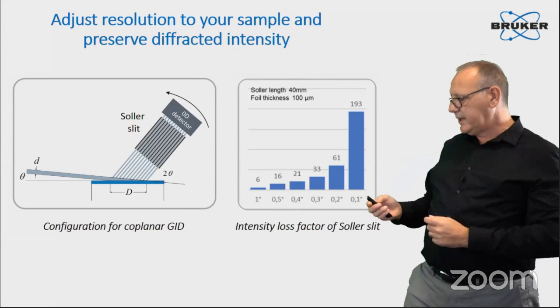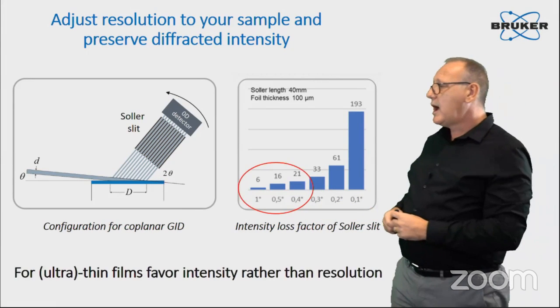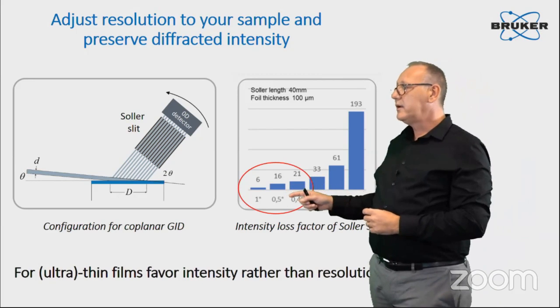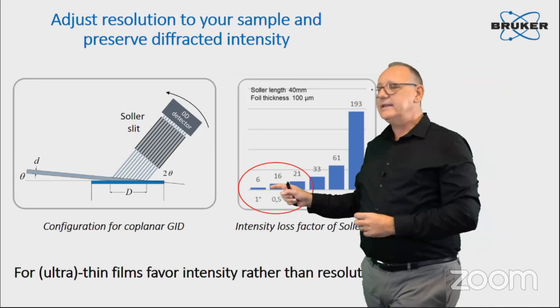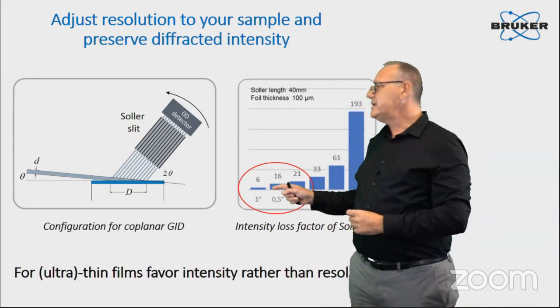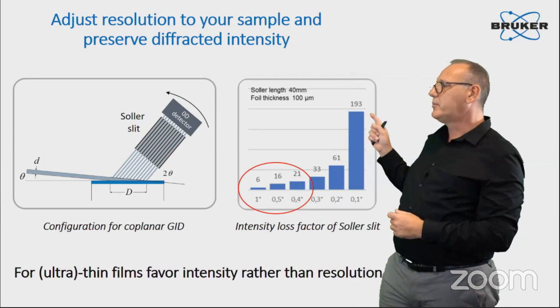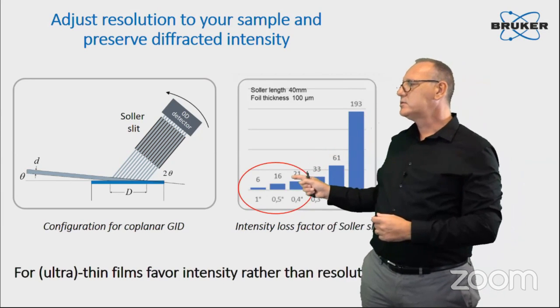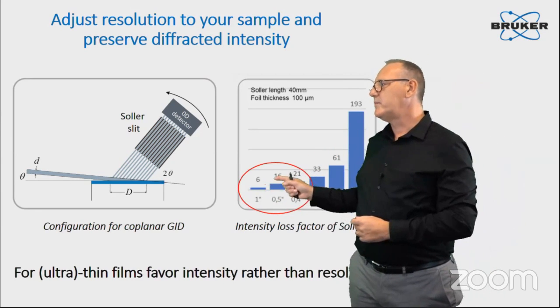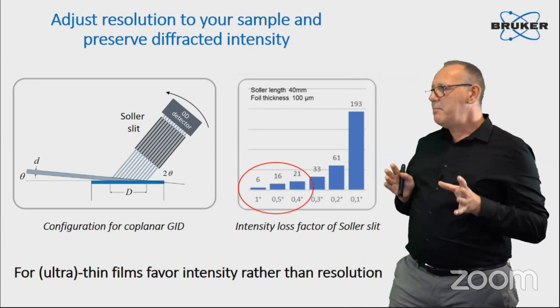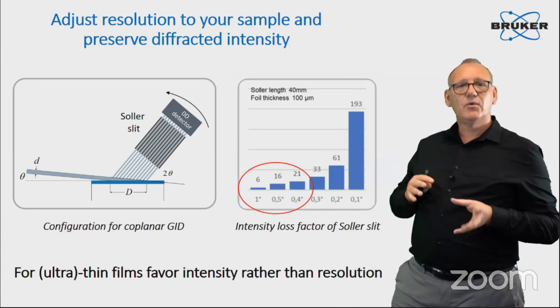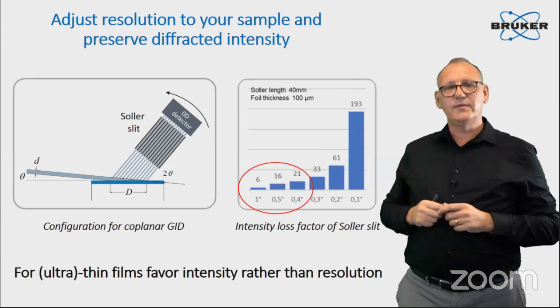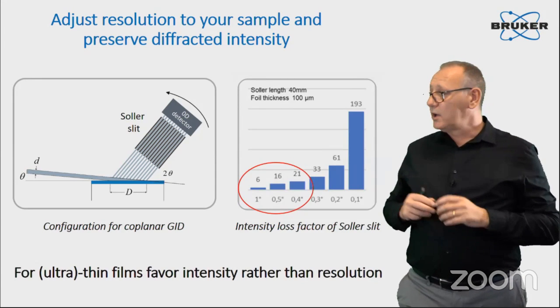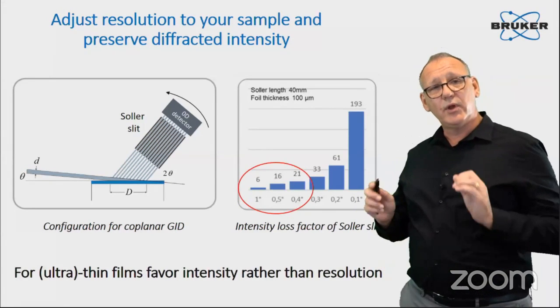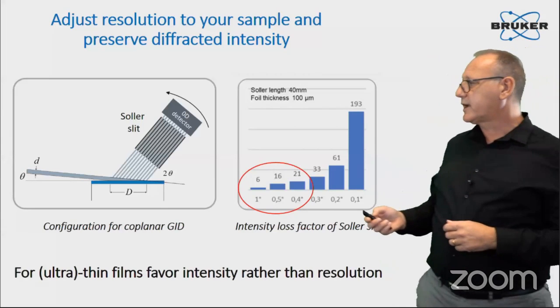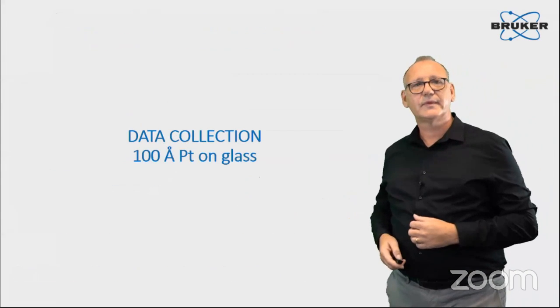But I would say for ultra-thin film, I would rather focus on the one that cuts the least intensity. Less intensity than here. Here we lose about 2 orders of magnitude. Here we lose maybe a factor of 1 order of magnitude. So again, better favor intensity rather than the resolution for thin film diffraction. So let's now measure our sample with an optimized setup and see what kind of data quality we can get.